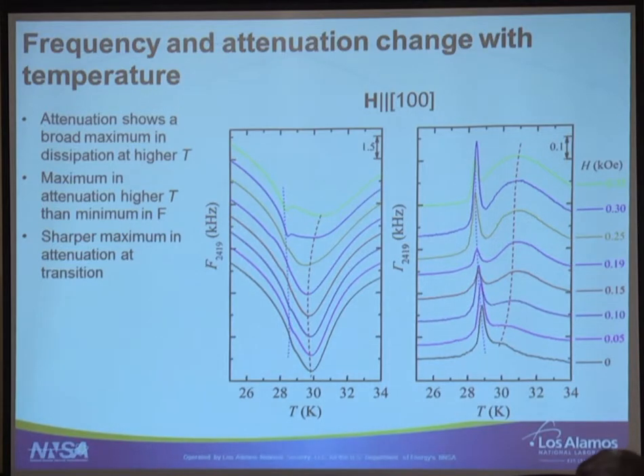So what it's telling you partly is that you have a subsystem that are the spins, and they are not the only thing that you have in your system. But if your interpretation would be correct, that means that all the fluctuations are 2 Kelvin ahead, and then the spin system acts. Yeah, we're also seeing that when we put field, these fluctuations are enhanced. You can see this is zero field, this is with field. So the fluctuations are field sensitive. That will tell you that spins are also playing an important role.